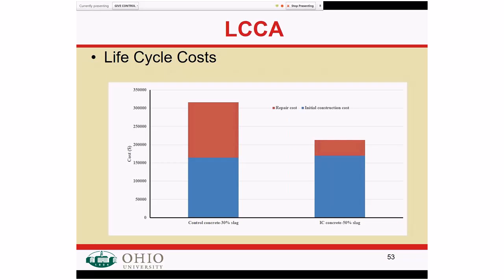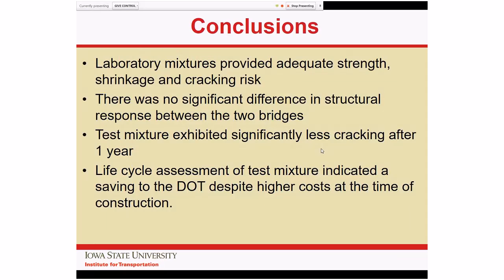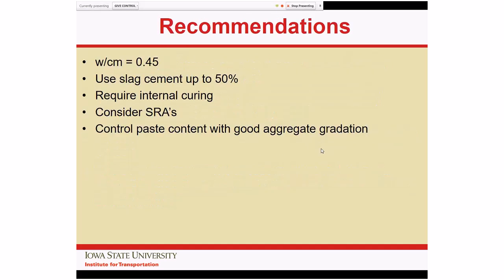So even with a fairly significant handling and premium delivery cost, the premium compared to the total cost of the bridge was relatively small. And when you compare that to the costs of maintaining the system over a 20, 30, 40, 50 year cycle, it's pretty small. And so we still believe that from a life cycle point of view, the system is eminently beneficial. Lab mixtures provided aggregates with adequate strength, shrinkage, and cracking risk. There was no difference in structural performance between the two bridges. We have shown significantly less cracking after 1 year, and life cycle assessment seemed to indicate that we're still better off by taking this approach.